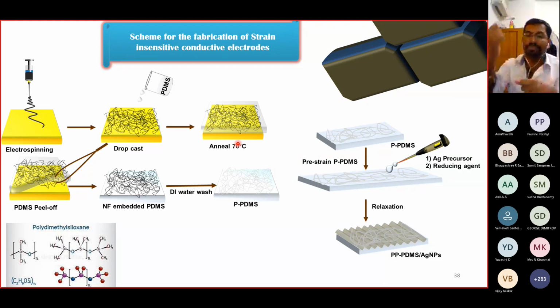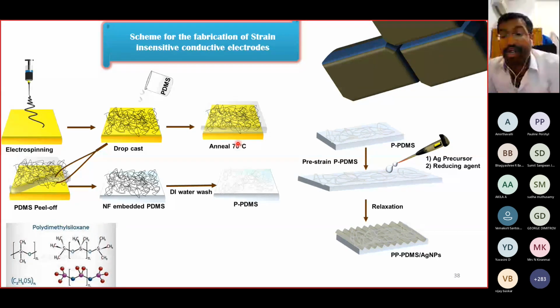We are going to pre-strain them and form some conductive nanoparticles. For that, I choose silver. We use a traditional method called precursor plus reducing agent to form silver nanoparticles. And this is how the structure of our polymers looks.